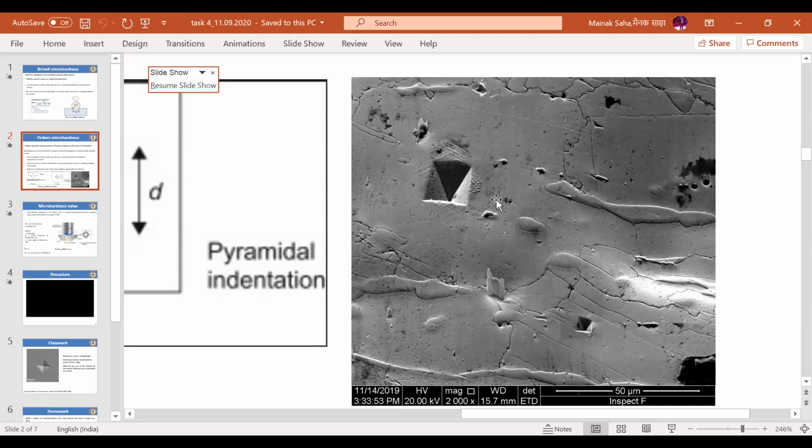So make a note of this. These slip lines are the manifestation of localized plastic deformation in any material during indentation. They develop during indentation, and you will find them very common in the near vicinity of any indent in any material. It doesn't matter what the shape of the indentation is. These lines indicate that the material is going to deform plastically at that load.